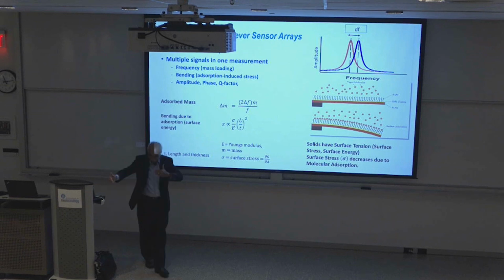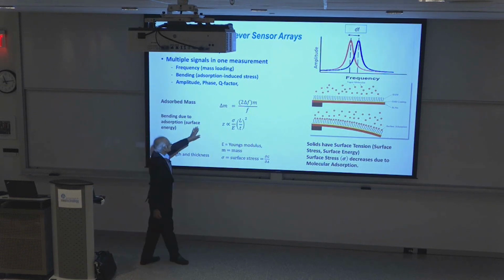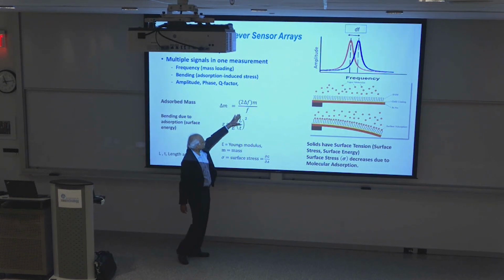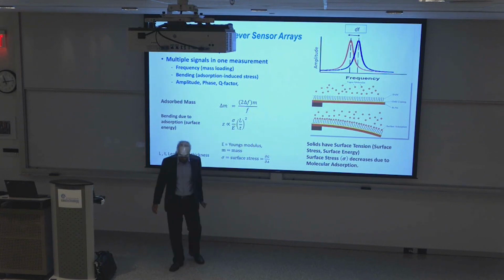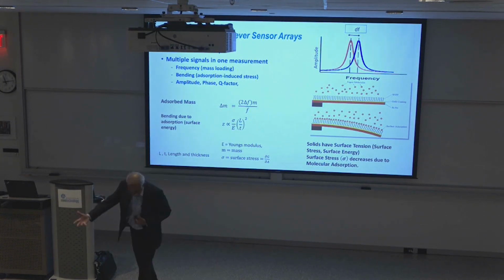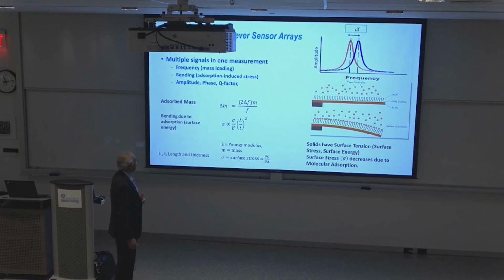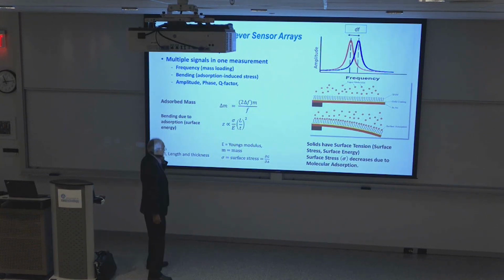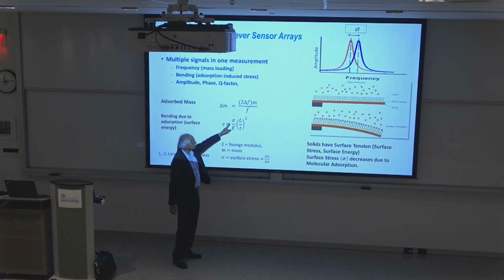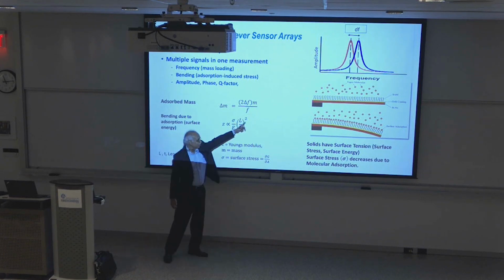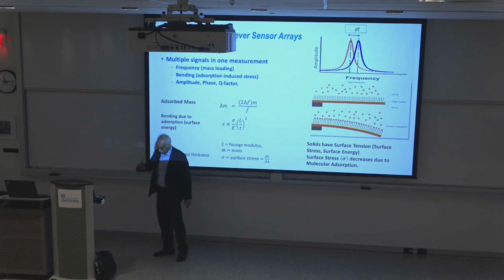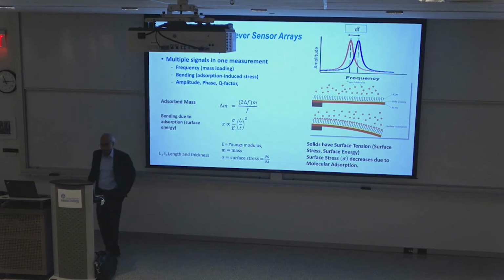So basically, you have to remember that change in mass is proportional to change in frequency, times the original mass of the cantilever divided by the original frequency. And the bending is related to surface stress divided by Young's modulus and a geometrical factor which will enhance the bending. So if you make the cantilever longer and thinner, you get a better signal. That can be easily measured.